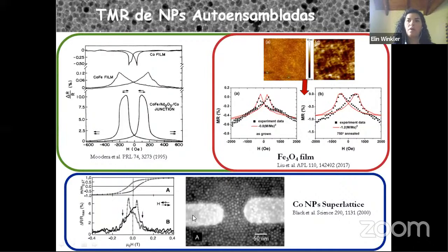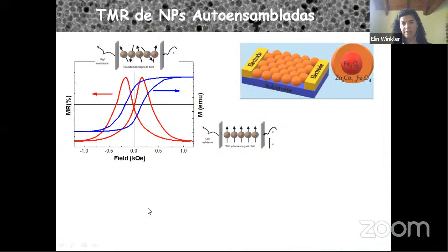So now we think, from what we found previously, we can modulate the coercive field in core shell nanoparticles by systematically tuning the shell of the nanoparticle. So we can fabricate devices where we can move the maximum of the magnetoresistance. So how can we do that? In this case, our plan was to fabricate magnetite, which is a half metallic compound.